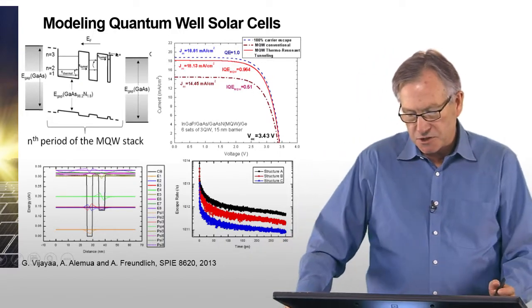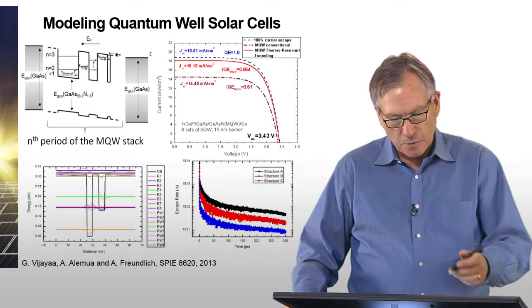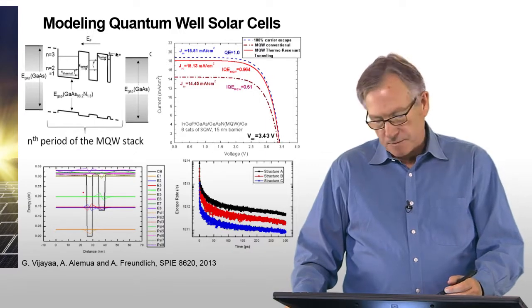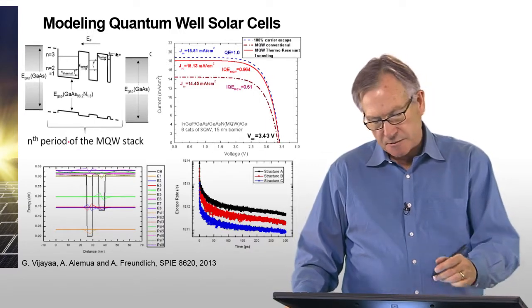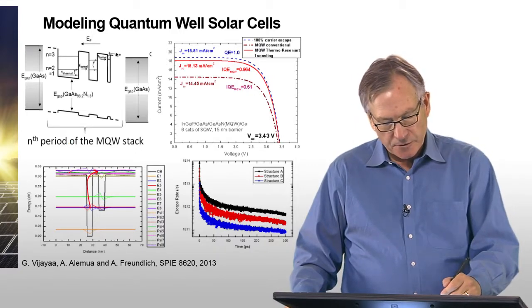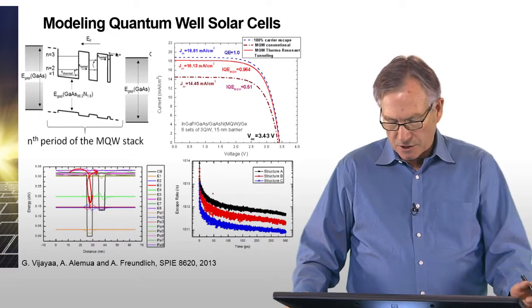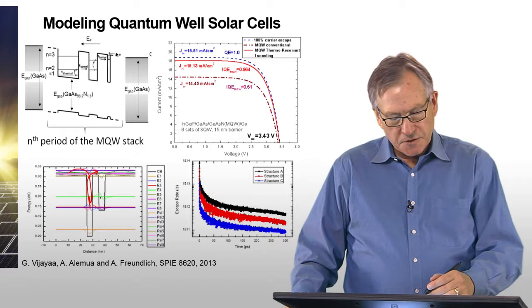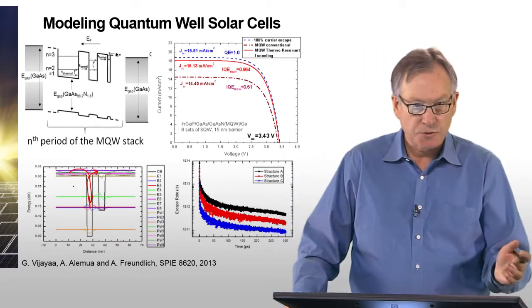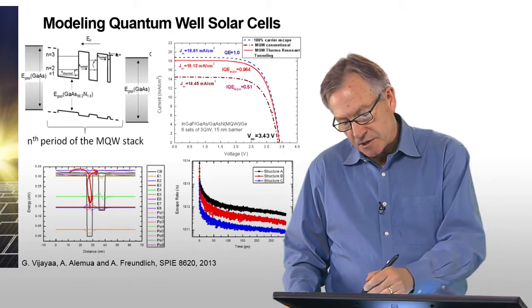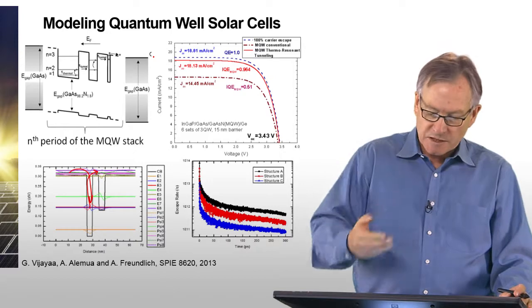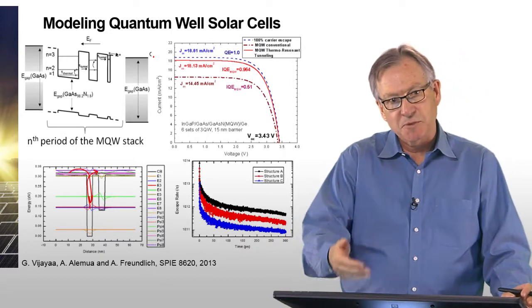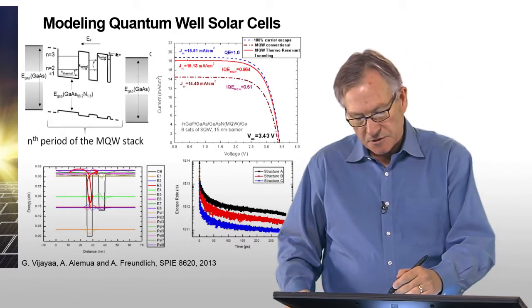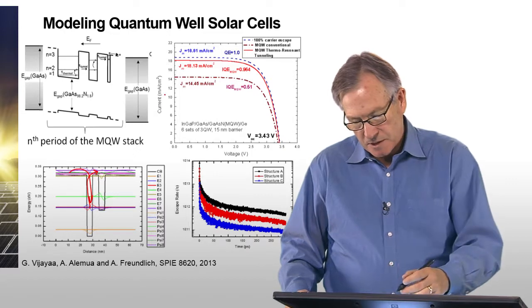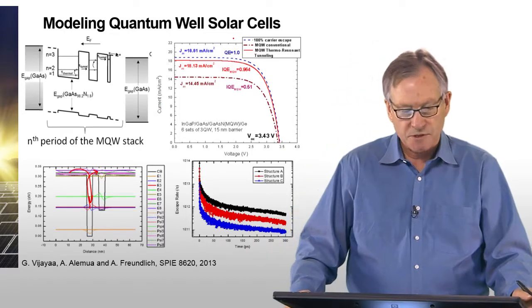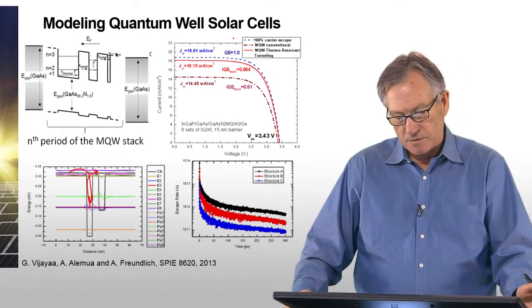And these are calculations and, again, evidence of a multi-scale approach. We model the electronic structure, then we model, basically using Monte Carlo, the carrier relaxation dynamics. In other words, how fast do carriers move out of here and how fast are carriers captured? This is a plot of the escape rate. And we feed this information then into a continuum model, such as the drift diffusion or hydrodynamic model I mentioned earlier, and you use that to calculate the current voltage characteristics. So we use that escape time that's simulated microscopically in a macroscopic simulation to simulate the current voltage characteristics and look at the predicted improvement of the efficiency based on different lifetimes assumed for this escape process. So this is just an illustration of a multi-scale approach.